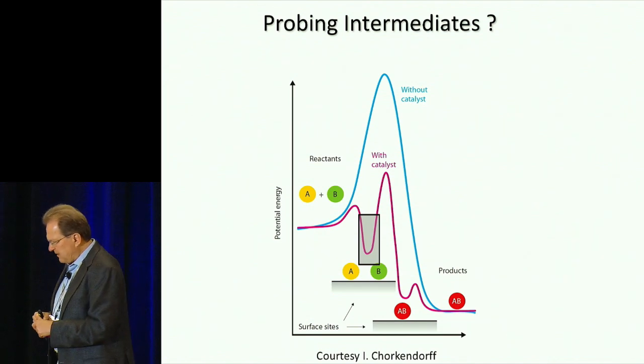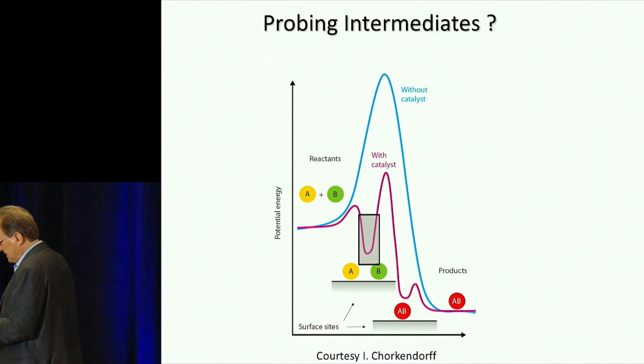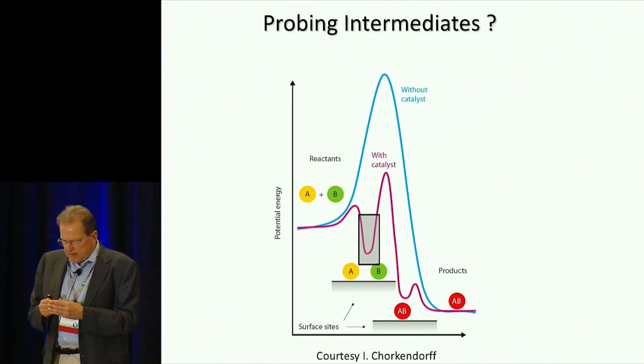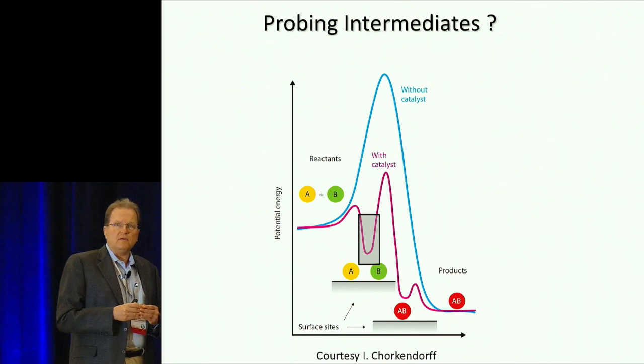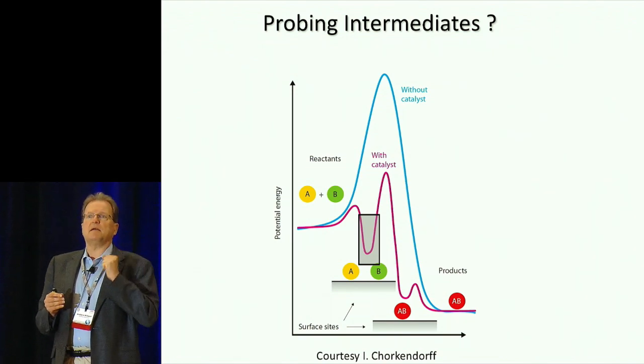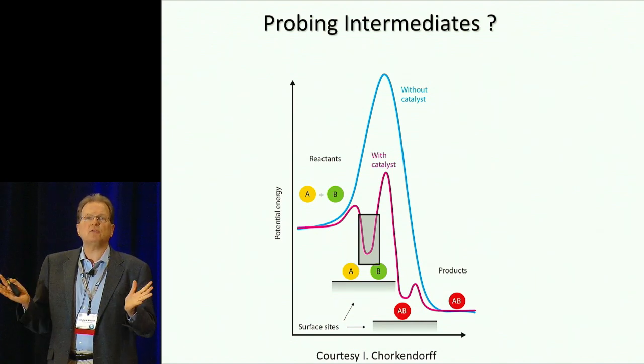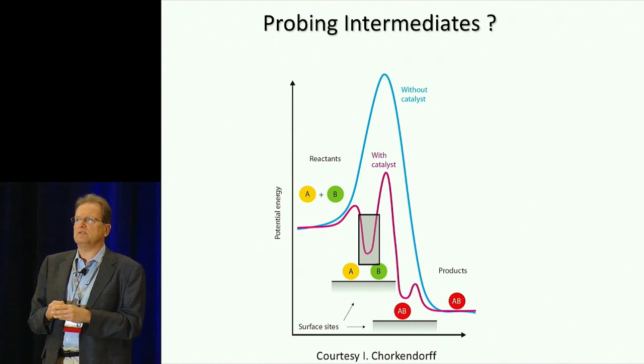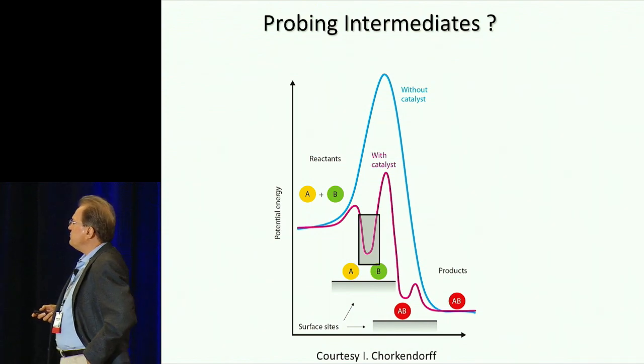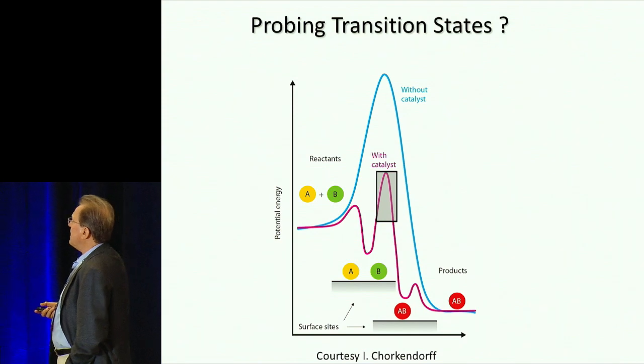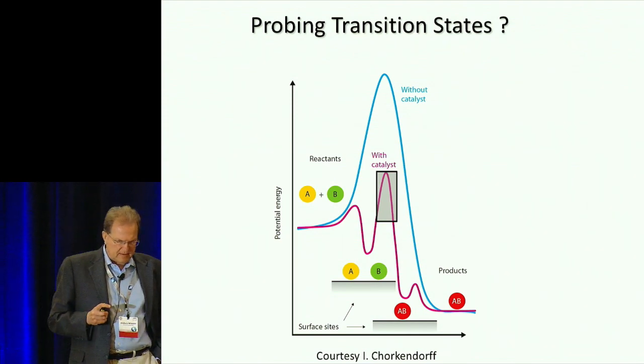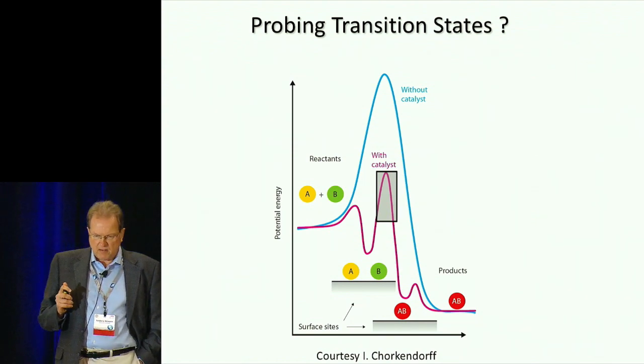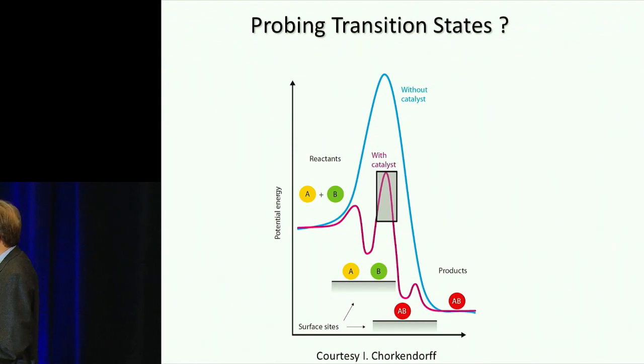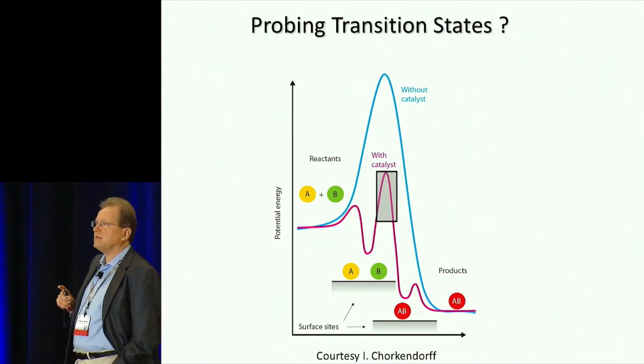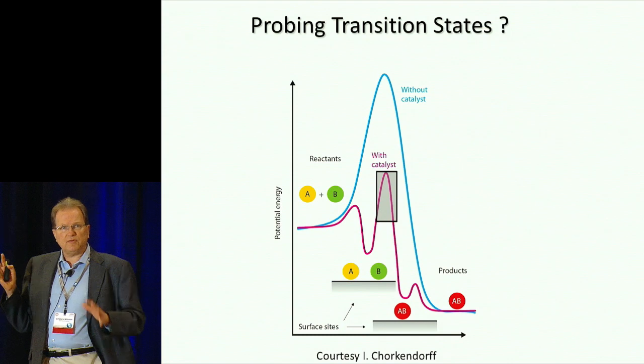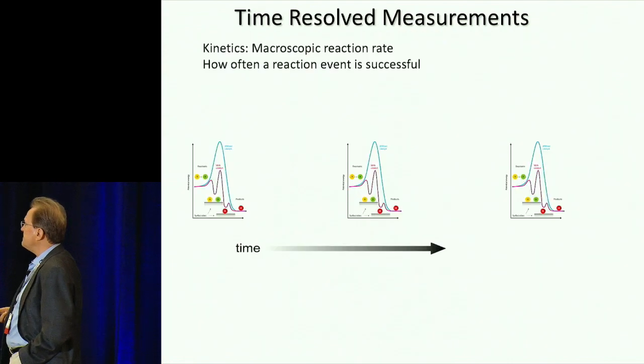And often people are trying to do this with operando spectroscopies, let's say at SSRL, but the important intermediate might be very short-lived. They might only live for a very short time. And under steady state conditions, the population of them is almost zero. It's a very small population. So we need to develop techniques so we can populate them very quickly to see them. The other thing is, can we probe transition states? And that was actually our CO2 study that was published in Science 2015. I am not going to talk about that so much today, but of course that is also very important. Both of these, the intermediate and the transition state, can we see these?